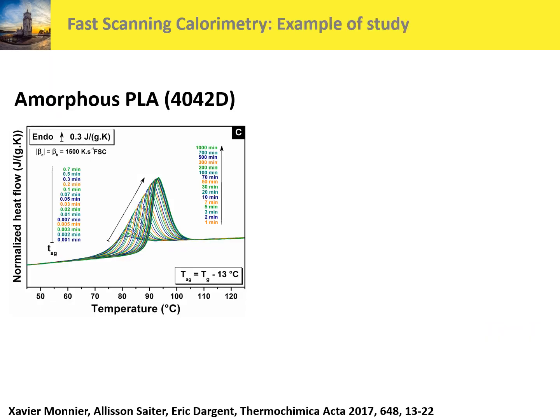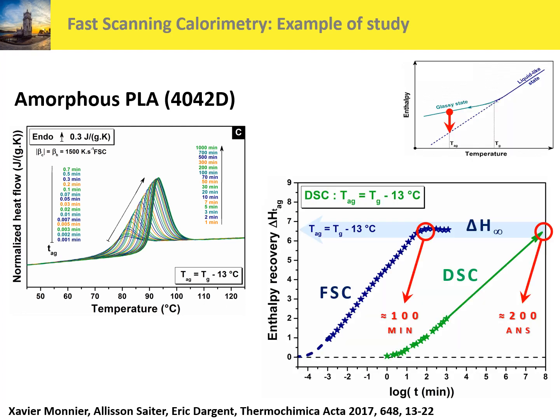To illustrate this, I propose to show you an example of aging study with amorphous PLA. These are the experimental curves obtained by the FSC technique for an aging temperature 13 degrees C below the glass transition temperature and for cooling and heating rates of 1500 Kelvin per second. From these curves, we estimated the enthalpy recovery, and as you can see here, we reached the plateau corresponding to the equilibrium state in 100 minutes. By comparison, we will need approximately 200 years for the same thing by classical DSC. So FSC offers the possibility to accelerate the physical aging process.